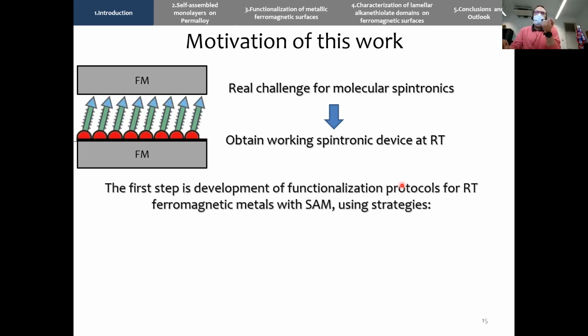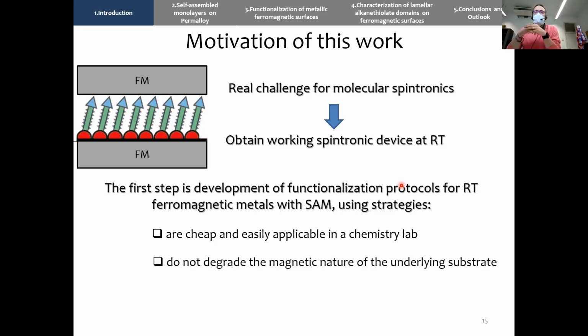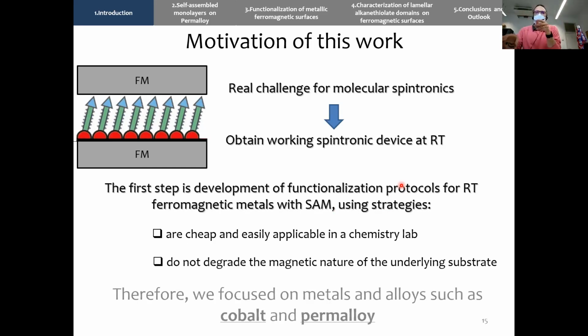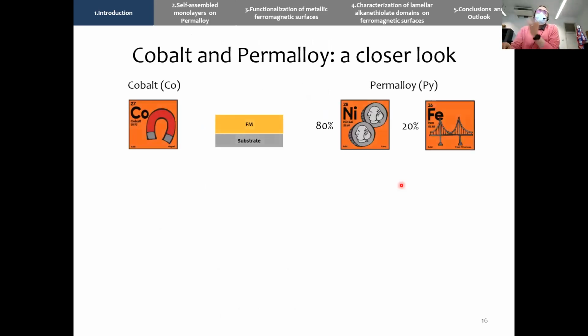But first, we have to start with the chemical modification of the bottom electrode, the ferromagnetic electrode, with a SAM. And we wanted to do this with cheap and easily applicable strategies in a chemistry lab. And we want to preserve the magnetic nature of the underlying substrate. And so we started working with cobalt and permalloy. These are our materials, cobalt and permalloy.